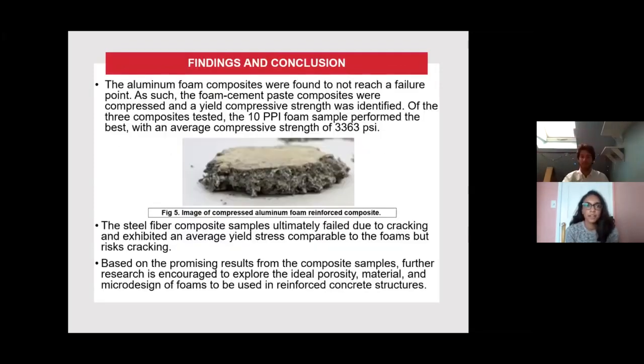Based on these findings, the aluminum foam composites were not able to reach a failure point, but they were able to have a maximum compressive strength and a yield compressive strength. Of the 3 aluminum foam samples, the 10 pores per inch foam sample performed the best, having an average yield strength of 3,363 psi. The steel fiber reinforced composite samples failed due to cracking, but also exhibited a good average yield stress compared to the foams.